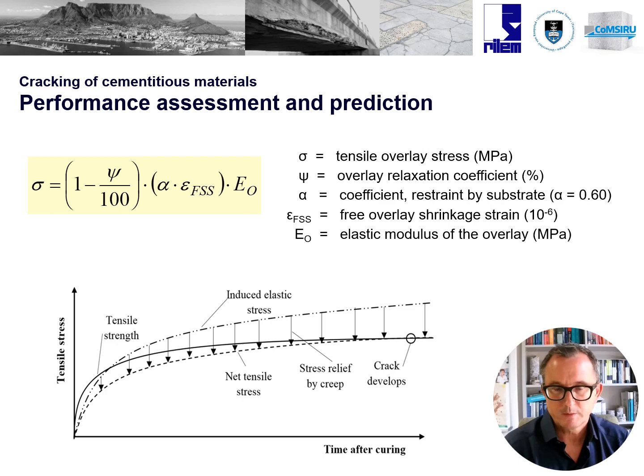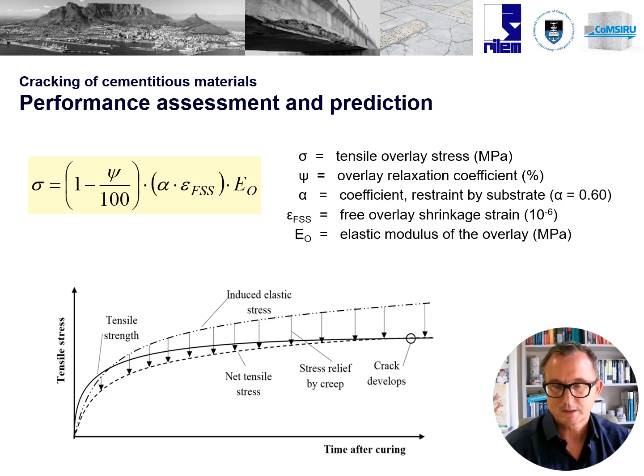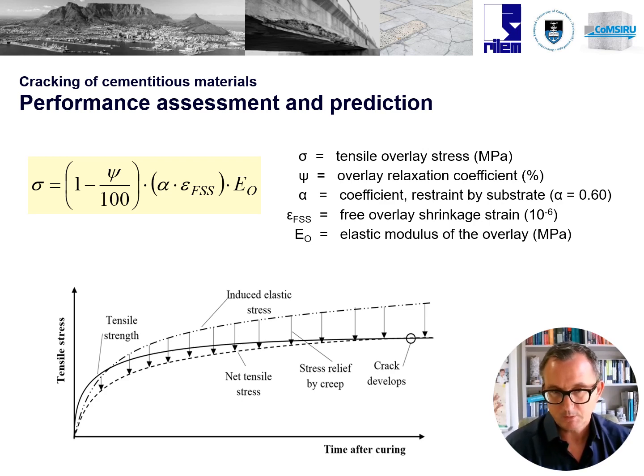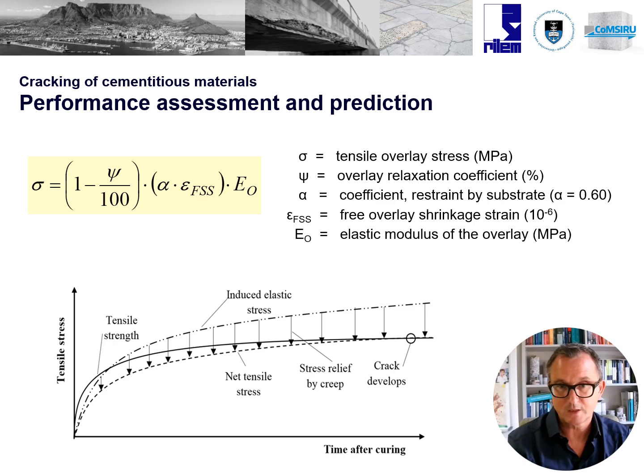Here you see a simplified illustration of how stresses develop inside a patch repair. The stress is simply a function of the restrained strain times the elastic modulus according to Hooke's law. The moment the tensile stresses exceed the tensile strength, cracking occurs. The stress in the equation is a function of creep — creep relaxation lowers the stresses in the repair mortar. It also depends on the degree of restraint, the amount of free shrinkage the patch repair tends to undergo, and the elastic modulus.